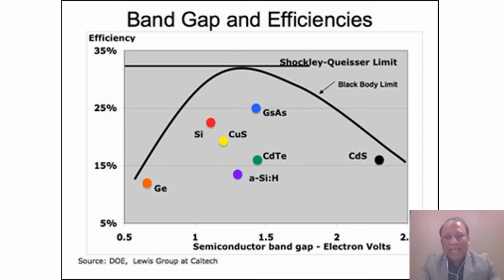So you see gallium arsenide, GaAs, is the best material for the time being, but perovskite structures also have band gaps around 1.55 electron volts. And the other thing about perovskites, these new materials, is that the band gap can be engineered, using some tricks to manipulate the band gap. So that is another possibility with perovskites.